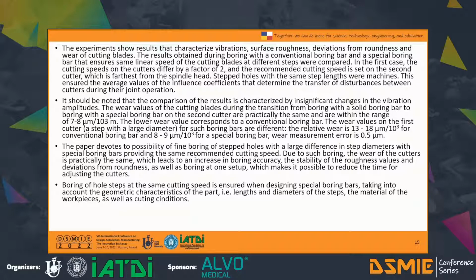The wear values of the cutting plates during the transition from boring with a solid boring bar to boring with a special boring bar on the second cutter are practically the same and are within the range of 7-8 micrometers per 10^3 meters. The lower wear value corresponds to a conventional boring bar. The wear values on the first cutter, a step with a large diameter, for such boring bars are different. The relative wear is 13-18 micrometers per 10^3 meters for the conventional boring bar and 8-9 micrometers per 10^3 meters for a special boring bar, where the measurement error is 0.5 micrometers.